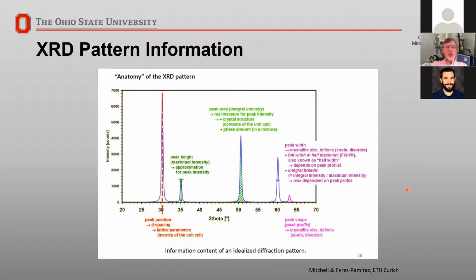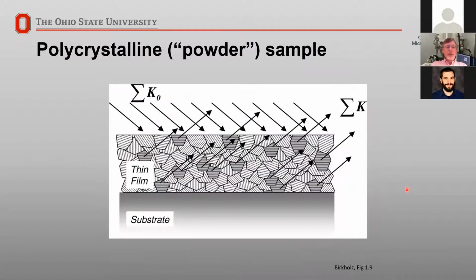Now, most of what we do here at CEMAS is called powder X-ray diffraction. So the assumption here is that we have an infinite number of small crystals that are randomly oriented. So as we come in with our X-ray beam and we look at our scattered radiation, the only lattice planes that are diffracting are those that are parallel to the surface. So we're only sampling some of these lattice planes, which is why we want to have a lot of crystallites in our beam to get a reasonable representation. And then as we scan through, we'll pick up these crystals and see what they are.